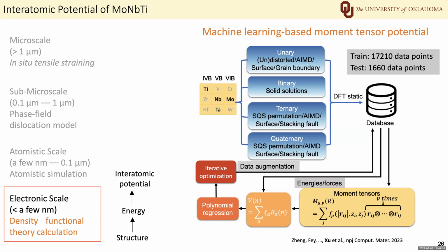In this potential, the atomic energy is expanded through a set of moment tensor functions of the local atomic environment. The data of both the pure metals and the alloys are used. The potential is then optimized using a polynomial regression. About 90% of the data points are used to train the potential, and about 10% to test it.